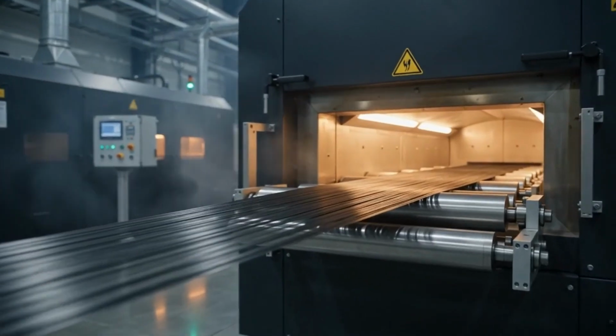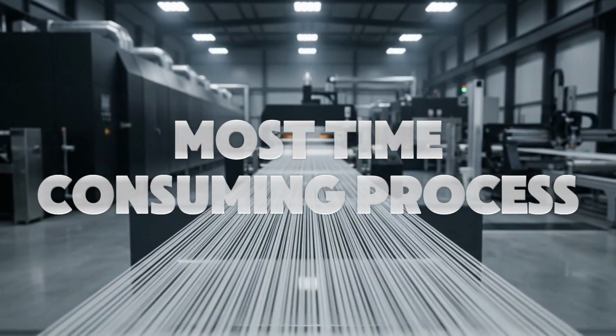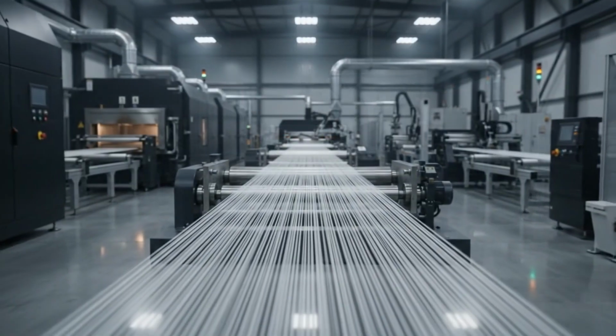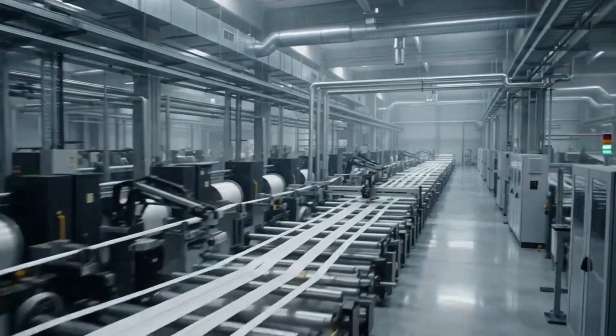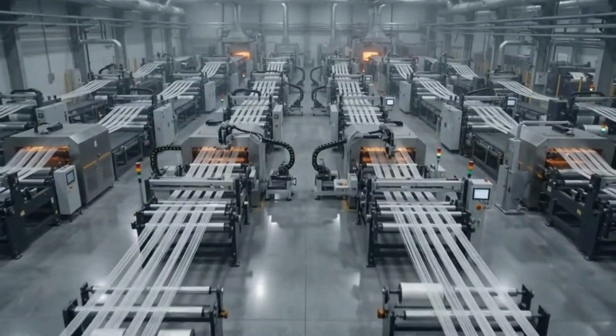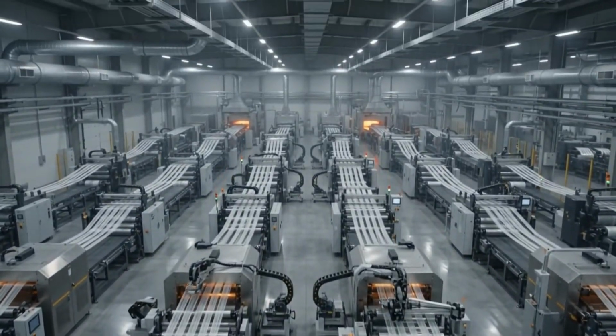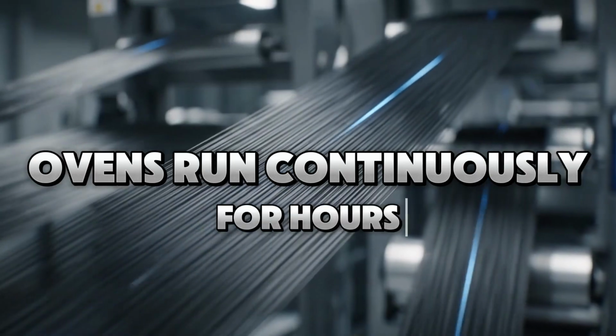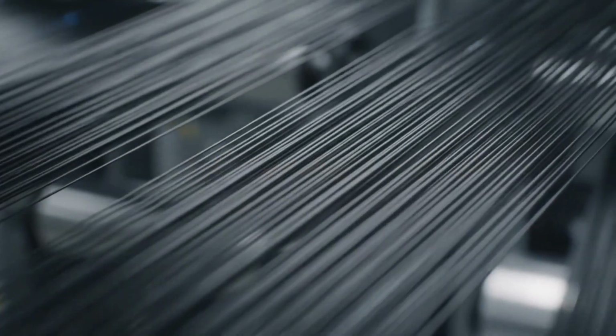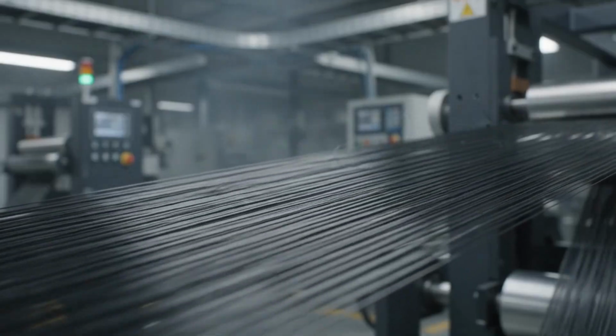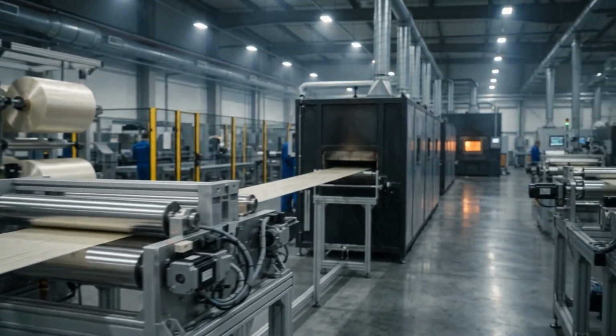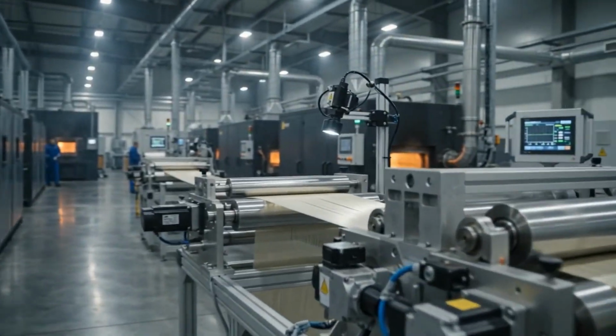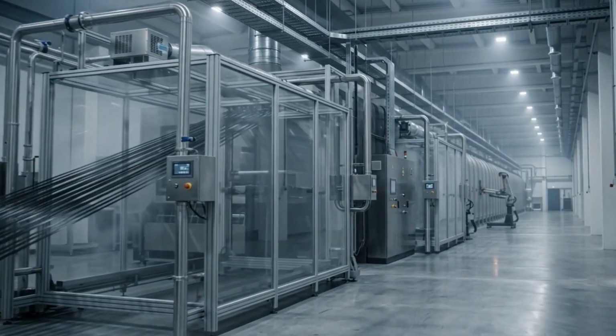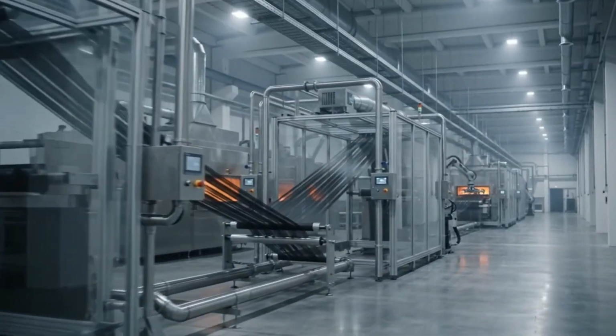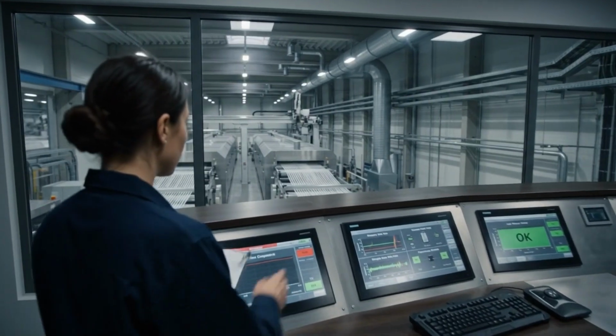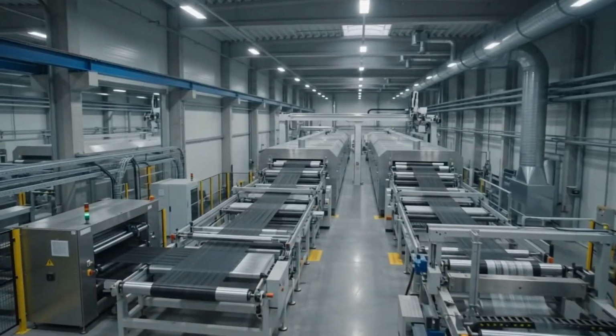But here's the thing. This is described in research literature as the most time-consuming process in the entire manufacturing chain. It cannot be rushed. The temperature window is narrow. Too hot and you create defects that destroy the fiber's properties. Too cool, and the transformation is incomplete. And these ovens run continuously, for hours, consuming enormous amounts of electricity, just to stabilize the fibers before the real heat even begins. This is the first thing manufacturers don't love advertising, because it reveals exactly why carbon fiber is so expensive and why cutting corners here is so tempting for cheaper producers. We'll come back to that in a moment, but first, let's talk about what happens when these stabilized fibers enter a completely different kind of furnace.